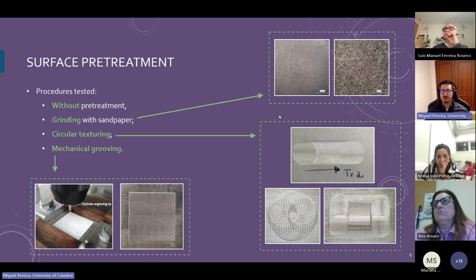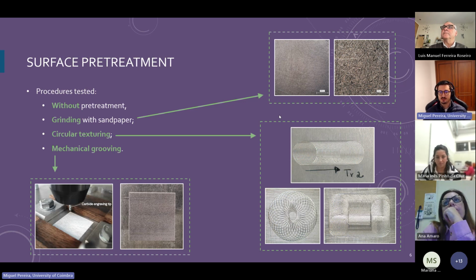Regarding the surface pretreatments that we tested, of course, we started by testing surface without pretreatment. Then we moved to a more simple process of just grinding. And then we tested two more unconventional processes for texturing the aluminum surface, which include circular texturing and mechanical groove.